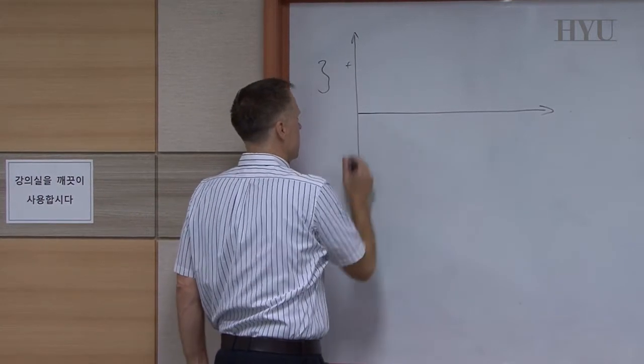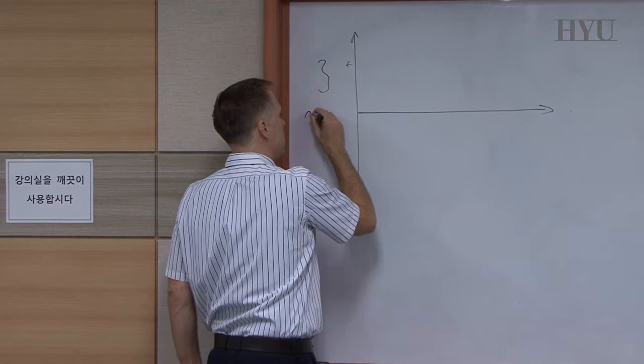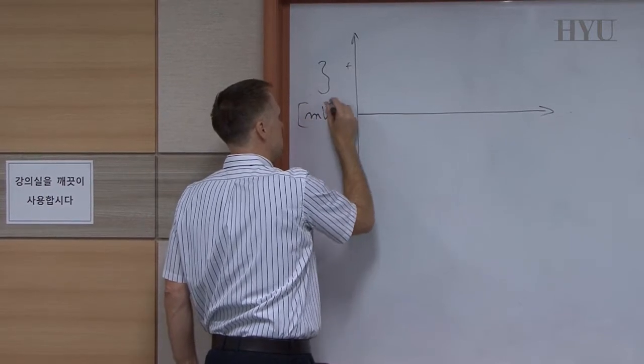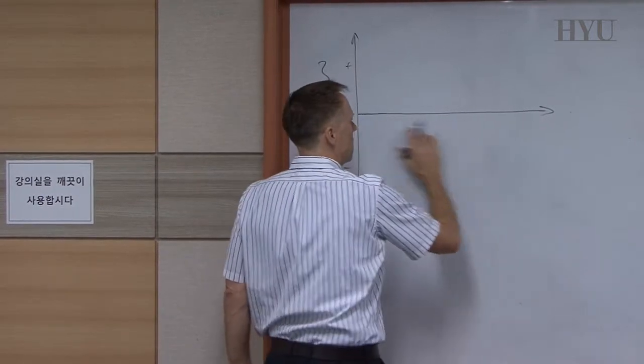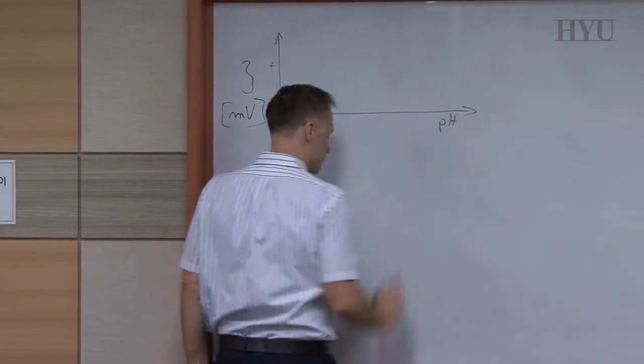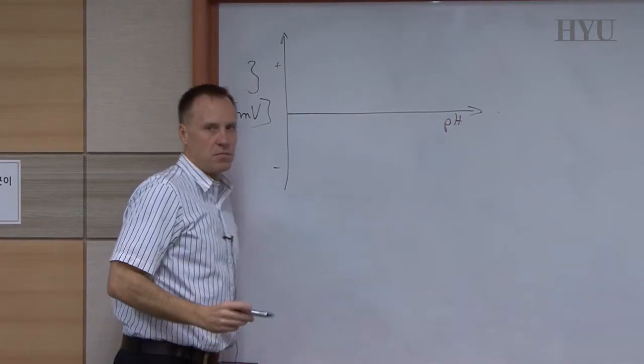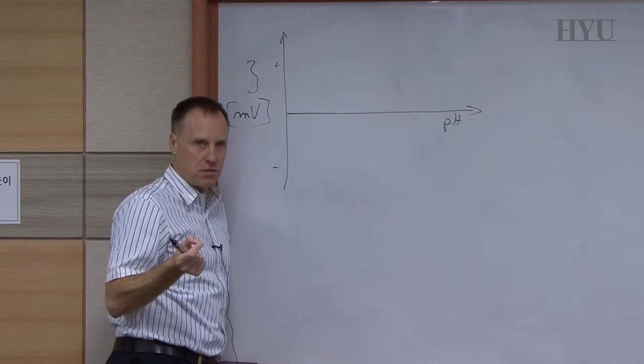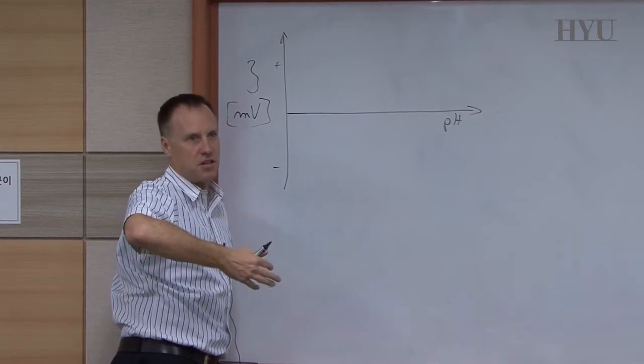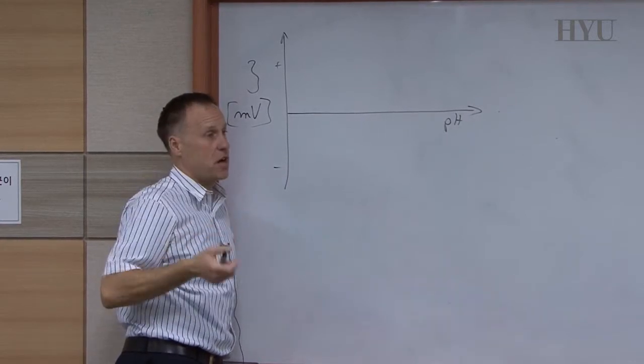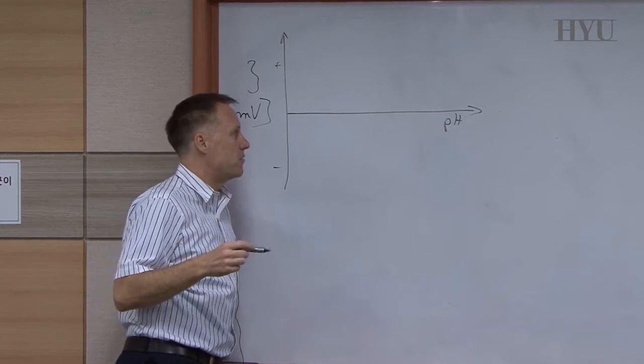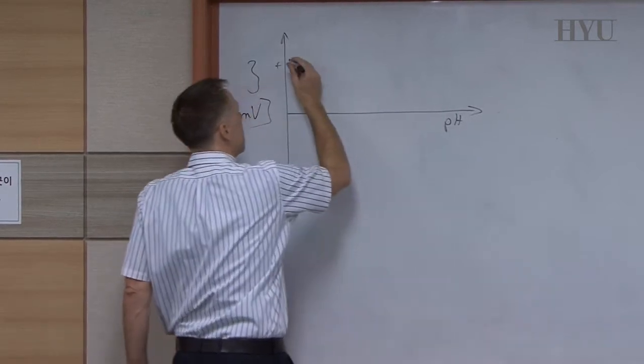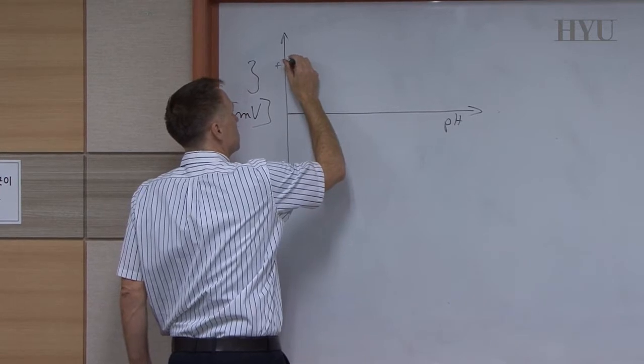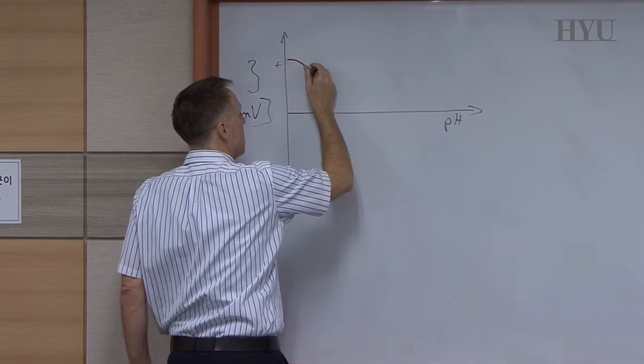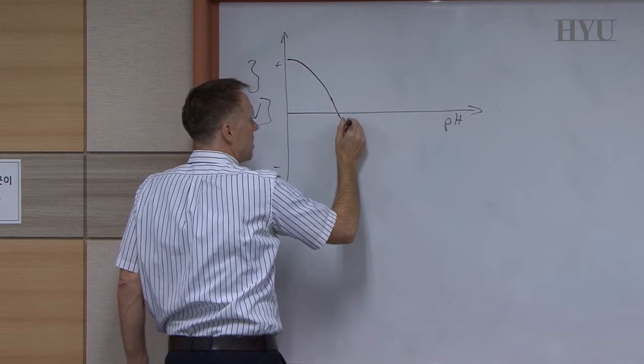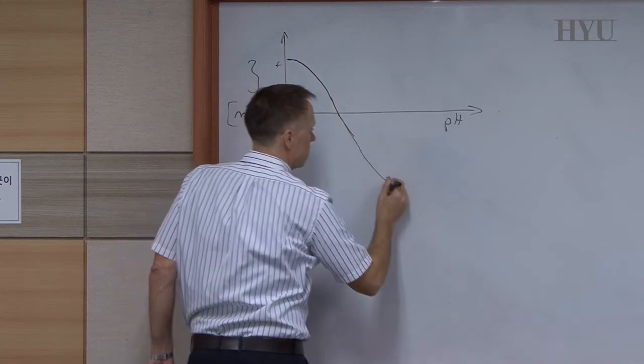And so, of course, this is positive, negative. And this is measured in millivolts. It's a potential, really. And we have a pH scale here. And as with most compounds, at a certain pH they are neutral. And then in acid, they charge up. In base, they lose charge and become negative. And for barium titanate, you start out with a positive potential. And around pH 6 or so, you go negative, and then it becomes more negative.